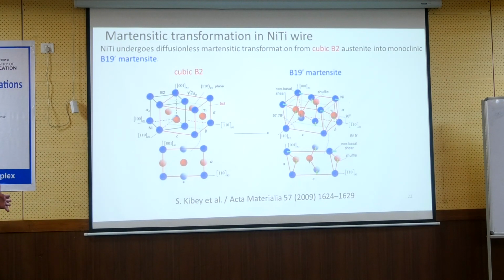And it is important, if one does the analysis in TEM, to consider the proper atomic positions. There is a jungle in the literature. Most people do not consider the atomic positions at all. Then they can index the pattern, but they have no idea about the intensities. So this scheme here shows the current level of understanding of the atomic positions. It is published in this article.